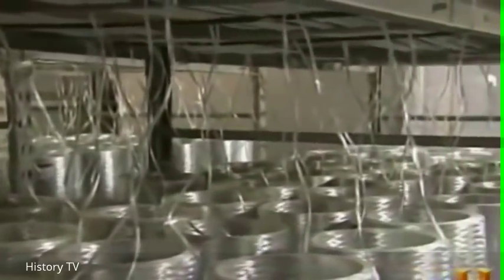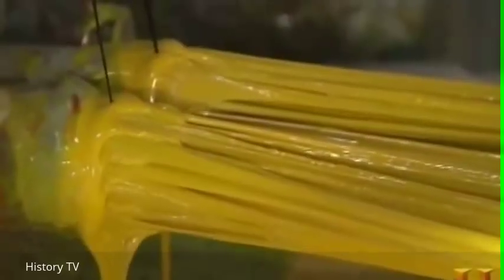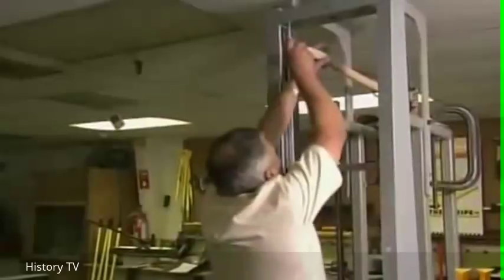Making a fiberglass handle begins with up to 150 bales of fiberglass. Each bale contains more than 100 strands. The strands undergo a process called pultrusion. It's pulled through the channels down toward the resin. The glass then proceeds into the die. The die compresses the glass. The die heats the resin-coated strands to 300 degrees, speeding the curing process. Then the glass meets the tractor that puts the pull in pultrusion. And it'll travel 30 feet down to our cutter. And that's how we make a fiberglass handle.